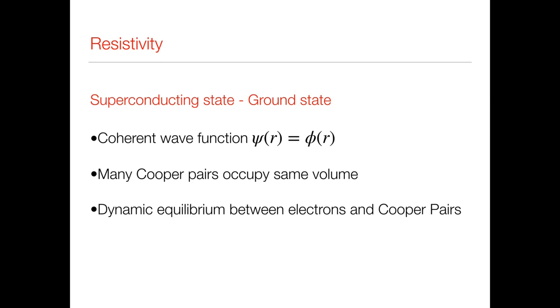Well, let's just remind ourselves that in the superconducting ground state we've got essentially a coherent wave function. Okay, we can write it like this. All of the Cooper pairs have the same wave function. Okay, this is coherent. Now, it's worth making the point that many Cooper pairs occupy the same volume. We saw earlier, a back of the envelope calculation gave us the separation of the Cooper pairs to be 2,000 angstroms. That's pretty big. There's going to be a very large number of Cooper pairs in that same volume. In fact, there will be millions of them. Okay, and there will be a sense of dynamic equilibrium between the normal electrons and the Cooper pairs.